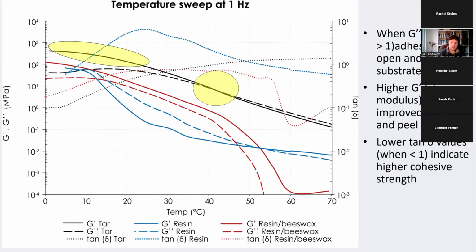Second of all, in an adhesive system, a higher storage modulus, the elastic portion, G prime, usually indicates improved impact and peel properties. So these are good. You want impact and peel resistance. Implements like spears or axes need to resist impact forces, and things like scrapers need to resist peel forces as the adhesive wants to get peeled out of the object that's on it. For birch bark tar, again, this is higher than the other two adhesives across the range of temperatures from about 0 to 25 that we tested here.